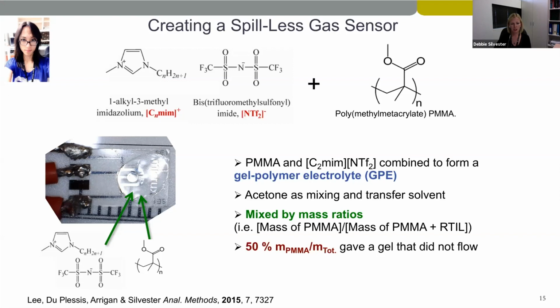And you can see a picture of the PMMA ionic liquid structure on the electrode. We used acetone to mix and transfer the gel polymer, and we had about a 50% mass ratio that gave a gel that didn't flow.